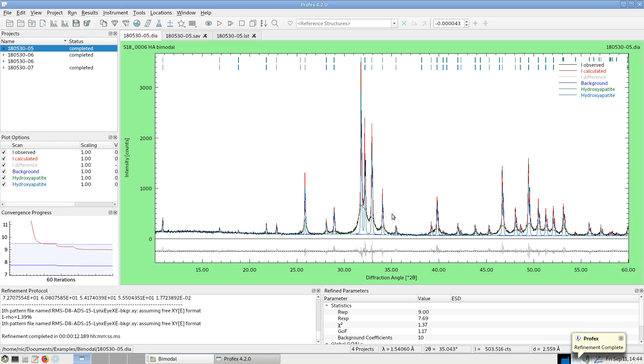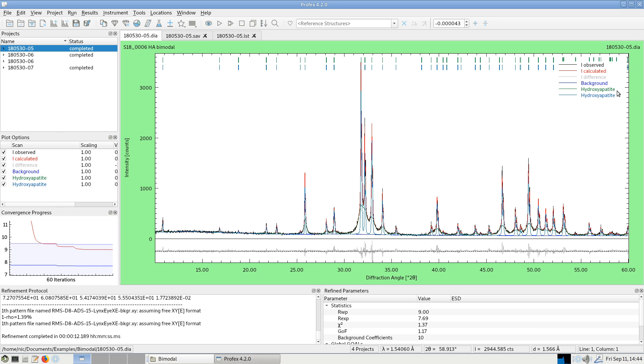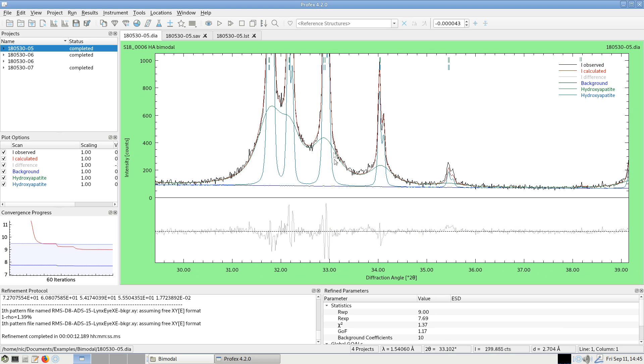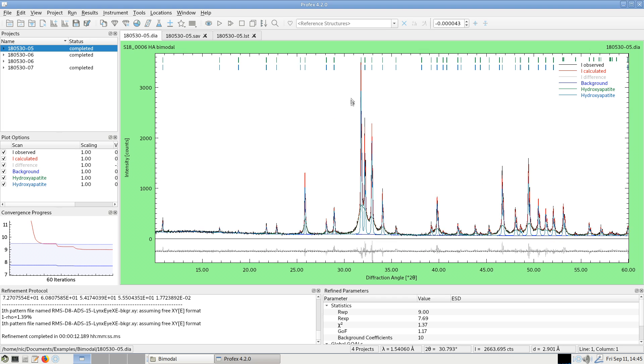We get a very good fit now and you can see two phases, both are now called hydroxyapatite. We should rename them to maybe hydroxyapatite coarse fraction and fine fraction or nanocrystalline and highly crystalline so we can separate them and also calculate the quantities. But for now they are just both called hydroxyapatite and you can see that the fit is very good. One of them matched the broad peaks and the other one matched the sharp peaks.